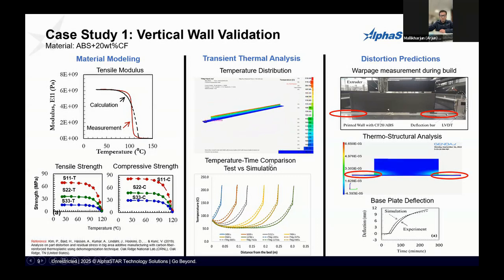Once we have the material modeling complete, the end product of the material modeling, if you look at the left side pillar, is a user material card, which has all the temperature dependent properties along with user defined damage and failure criteria. The user will specify this is the damage criteria I want to capture in my simulation. Once we have that, we go to thermal analysis, where bringing in the G-code that's being used to print, we simulate it and create a realistic build plate. In here, we have a build plate. On top of that, there is a thin aluminum sheet which is bolted down, on top of which it's printed. So we bring all that detail into the thermal analysis, because thermal is the backbone. So we have to get the right thermal response so that we can trust that thermal will predict the right mechanical response.